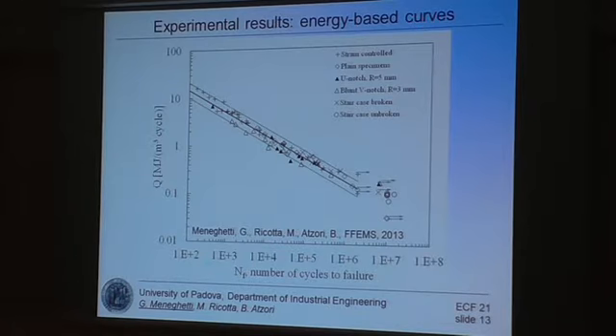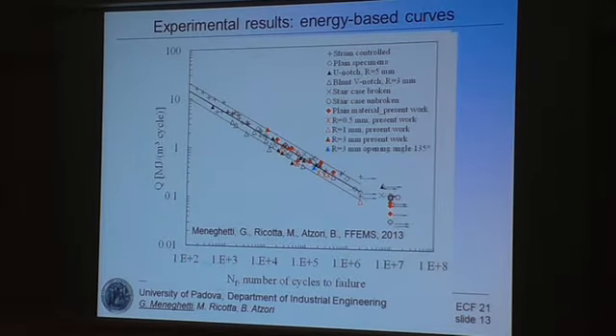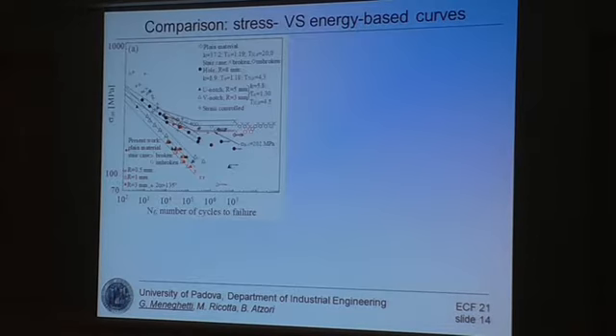Now, I would like to present the summary of the experimental results in terms of energy. You can see here a plot of previous results we have published in recent years. You can see here that we considered quite blunt notches with radii of 3 and 5 millimeters. Now, if we superimpose the results we have obtained in this case, where the notch radius was reduced down to 0.5 millimeters, you can see that they fall quite well in the same scatter band. But in order to appreciate this approach, I would like to show you the situation in the stress versus number of cycles to failure plane. You can see here the raw data, they are much scattered because the net section stress amplitude has been used here.